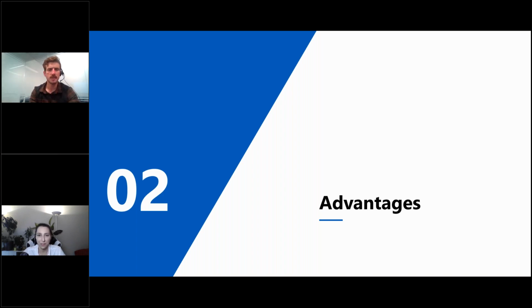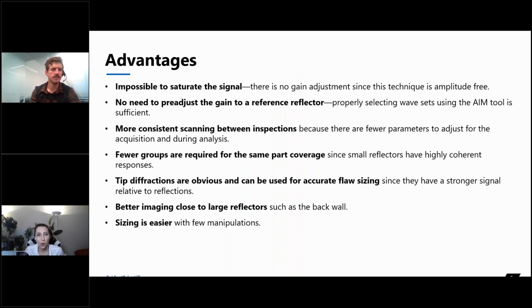Thanks, Trevor. All right, so as Trevor mentioned, there's really no gain, or we're not looking at amplitude anymore. It's an amplitude-free signal. What that means is that it is kind of impossible to saturate the signal, which is a good thing, because when you are saturated, as you might know, with PAUT or conventional UT or conventional TFM, then sometimes you need to go and do a rescan because you were way above your window.